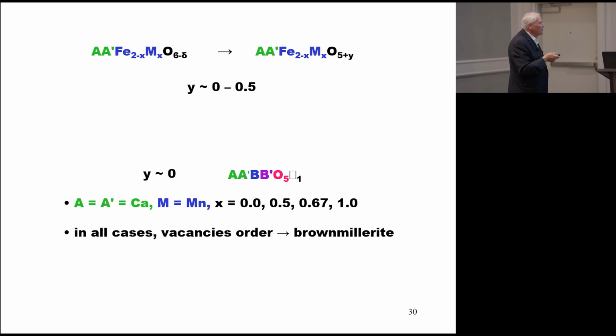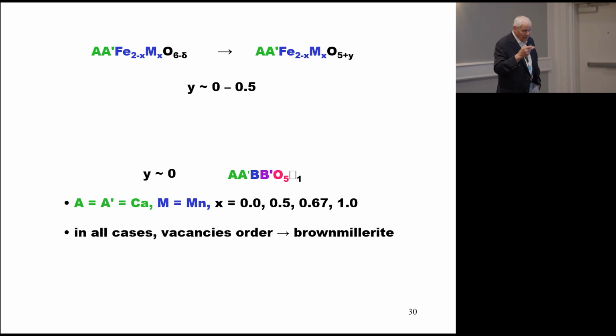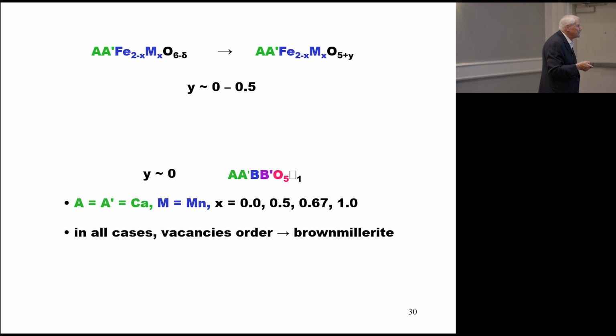we're going to look at some specific perovskites to start with, oxygen deficient perovskites. These are going to be based on iron and, for the most part, manganese. You can formulate them this way with 6 minus delta or 5 plus y. We'll choose the second representation, and we're going to focus on the y equals 0 cases where we have created about 16% of vacancies on the oxygen site.